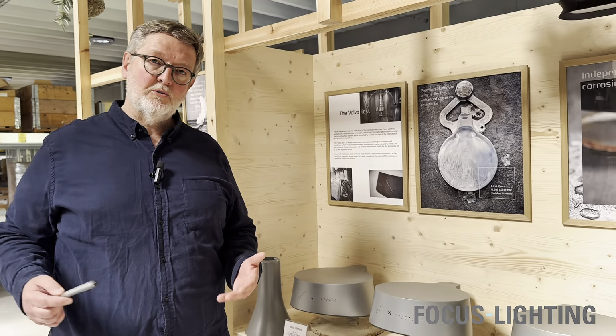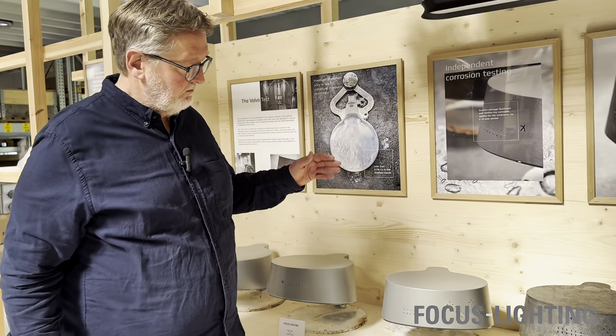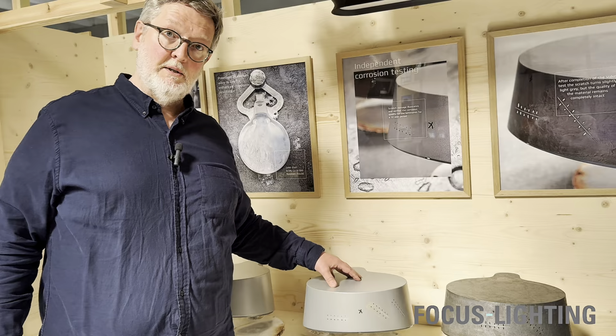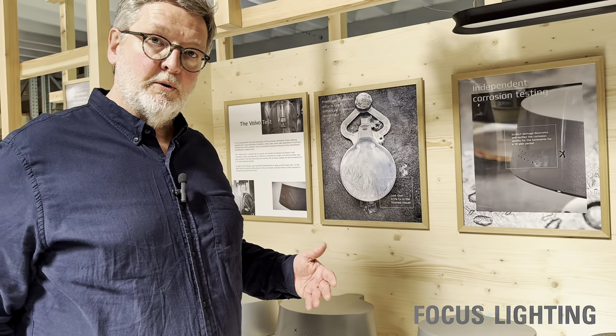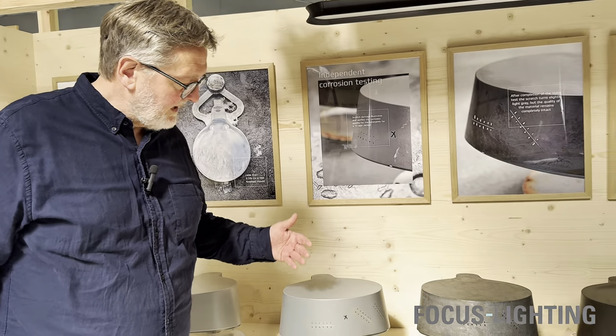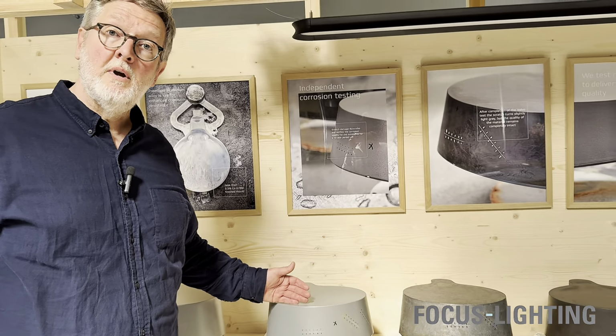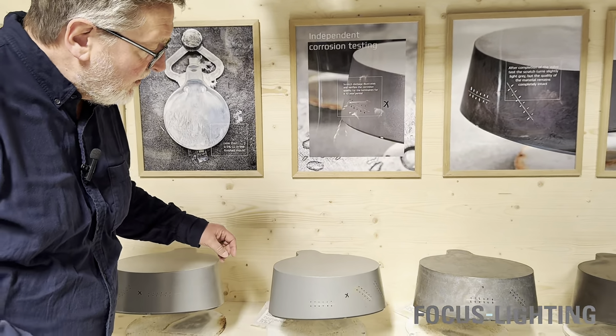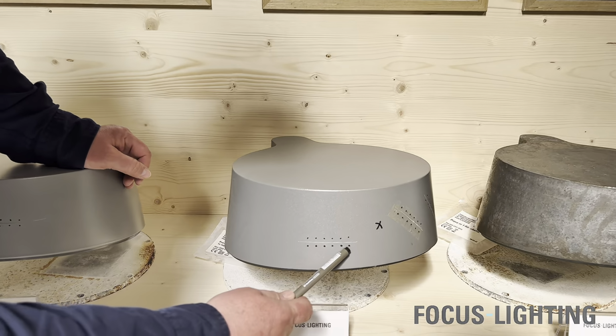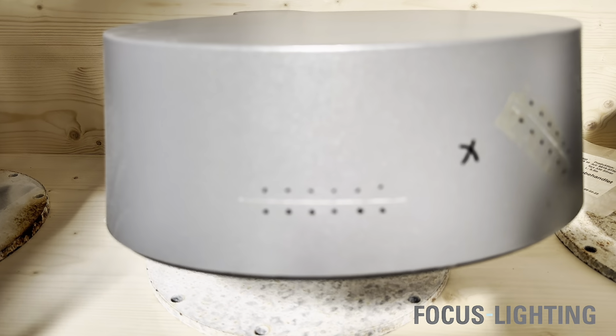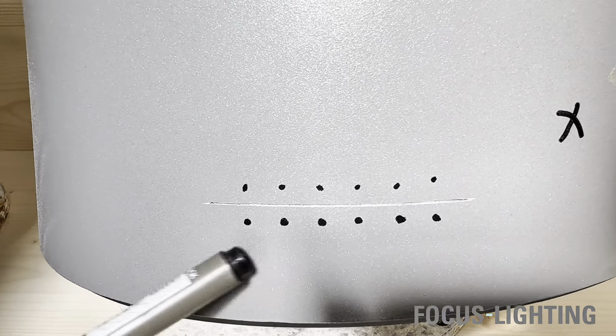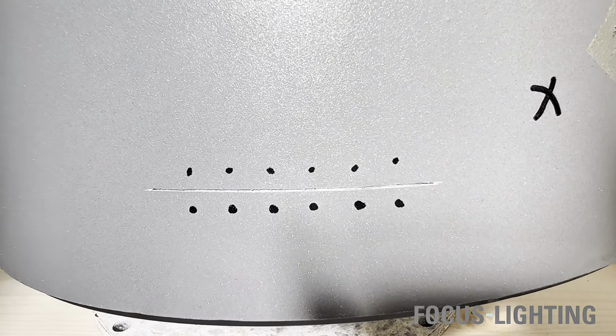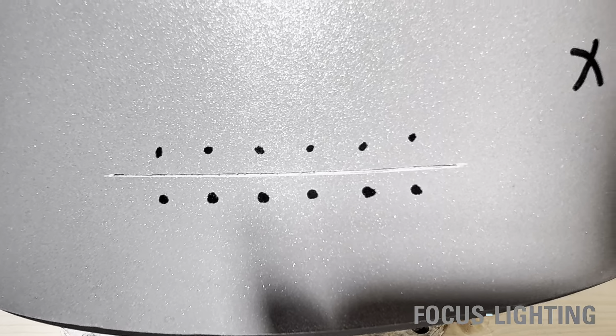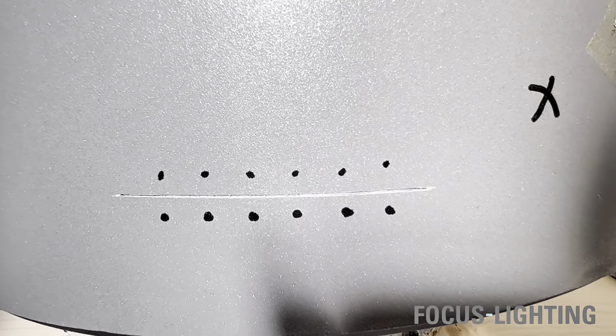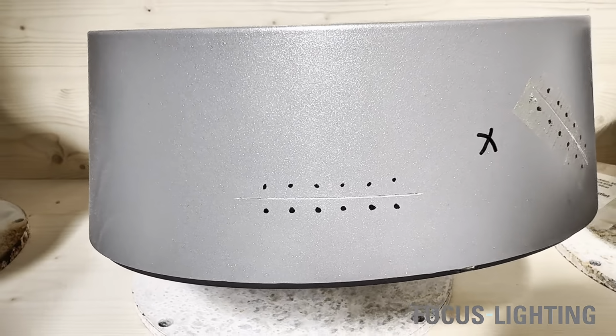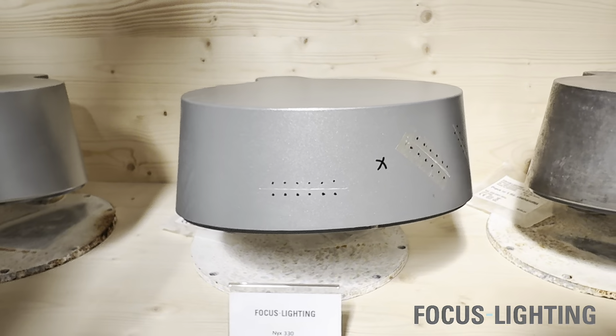But if we're moving into coastal areas, we also have the offering of what we call the C5 quality. There we have other measures in order to improve and make the surface even more robust. And if we go close to this one, again, looking at the scratch, there's actually no blistering around the scratch. And this is after 10 years of use in the field. So this is the best quality that we can provide for a high surface corrosion protection.